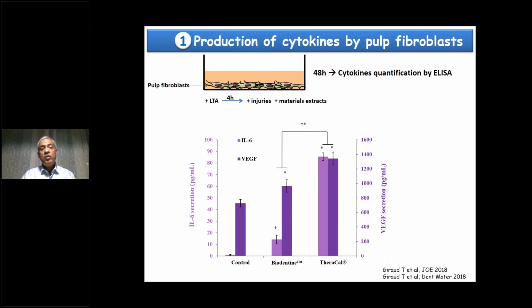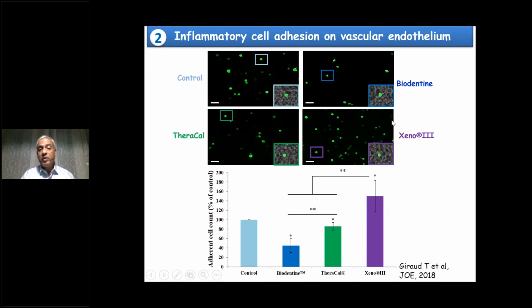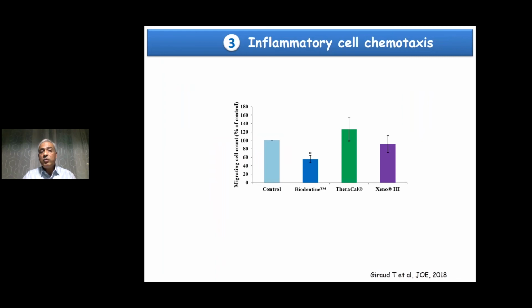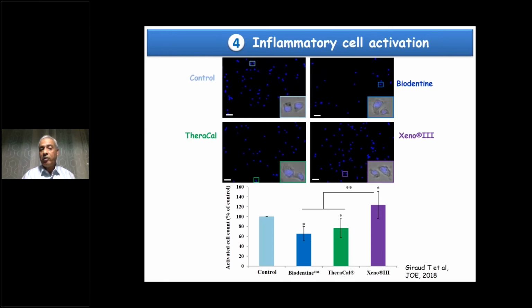Now, the next step was to look at inflammatory cell adhesion on vascular endothelium. Here you see the inflammatory cells on the endothelial cells that are behind. And you notice that when you have tricalcium silicates like Biodentine, you have a decreased adhesion of inflammatory cells on the endothelium. The third step was to look at chemotaxis, that is the attraction of inflammatory cells to the application site of the material. And you notice that Biodentine decreases the inflammatory cell chemotaxis towards the material application site, which means that it will decrease the inflammation. And the last step is the activation of these cells to carry out phagocytosis. When these cells are activated, they release hydrolytic enzymes, and they can induce lesions to the tissues.